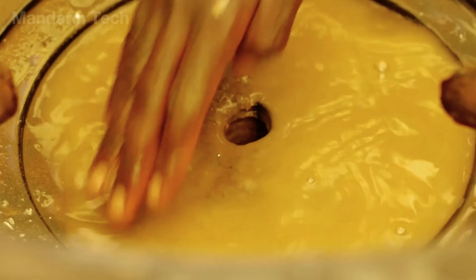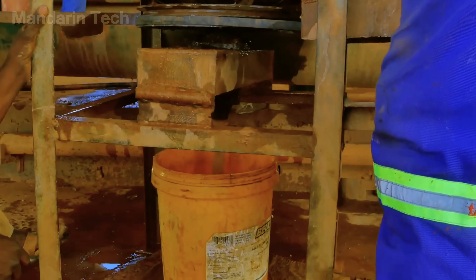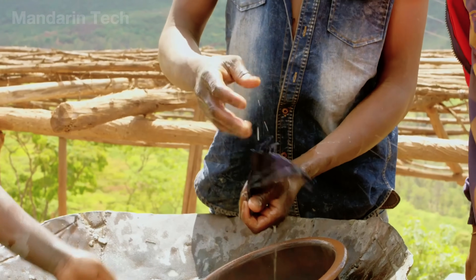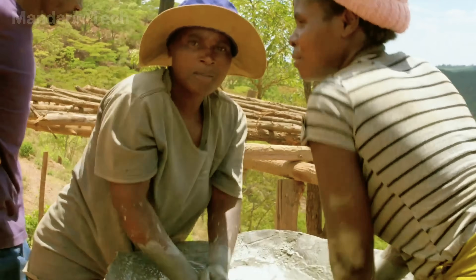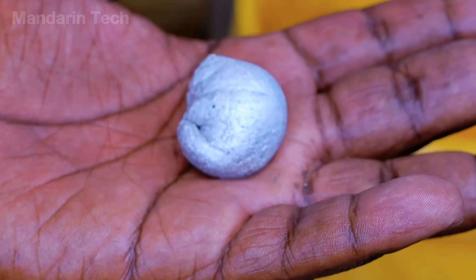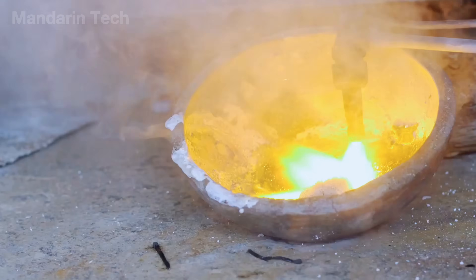When the crushing process is finished, the excess water is drained off, and the remaining material is moved for a step that is both more precise and far more dangerous: adding mercury. Even though mercury is notoriously toxic, capable of causing cancer and severe neurological disorders, it's still the only chemical people here can afford, and the only one that can dissolve gold, pulling it away from the remaining impurities. Workers knead this mercury-soaked mixture for 20 to 30 minutes until it thickens into a dense gray paste — an amalgam where gold and mercury fuse together. The lump is then heated, causing the mercury to evaporate and disappear into the air, leaving the raw gold behind.